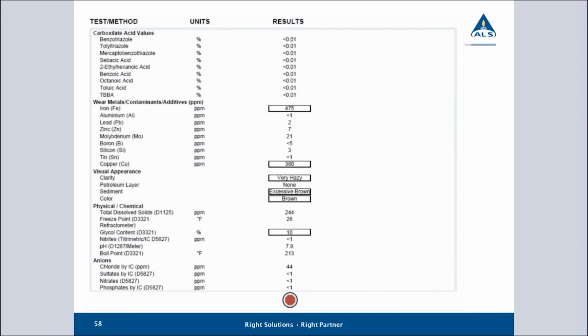Have another sample here of a very poor looking coolant. We've got extremely high iron level. We've got extremely high copper level. So a lot of corrosion going on in the system. We can see visible rust in the sample. And when we look at our additive levels, they are very, very low. So what we're looking at here is what looks like almost straight water in the system. Whatever coolant was originally in the system is long gone, has probably been constantly topped up with water until it's completely replaced the original coolant, and this has allowed a lot of corrosion to start taking place.